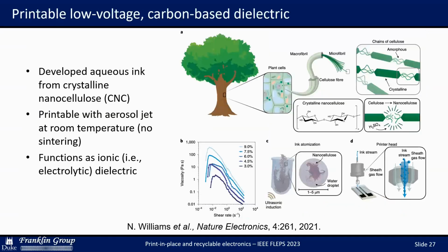So we took this technique of print-in-place devices that I showed you, and we replaced the insulating layer with a biodegradable printed dielectric. We used a material that's actually very well established in the printed community, including flexible electronics, which is nanocellulose. It's an extract of the fibrils from a plant, and you obtain it through acid hydrolysis. It's almost always used as a substrate, a biodegradable substrate for any other types of electronics. In our case, we developed it into an aqueous ink that is able to yield a dielectric.